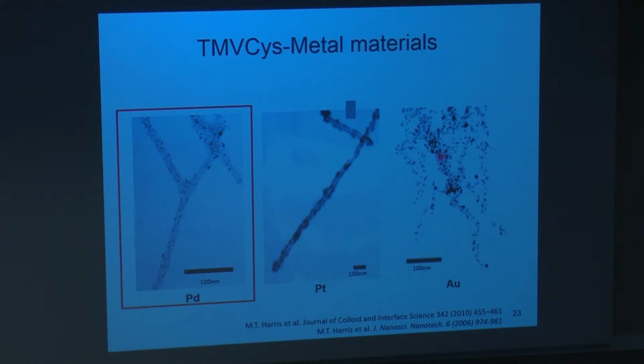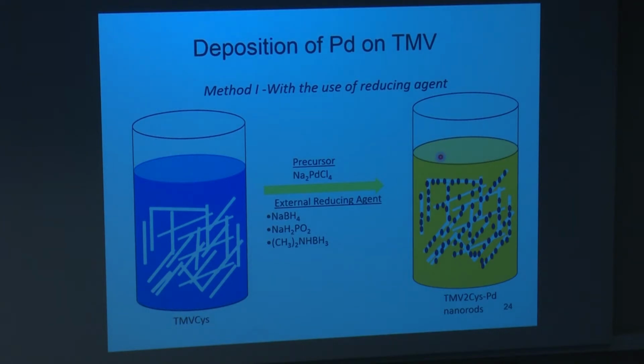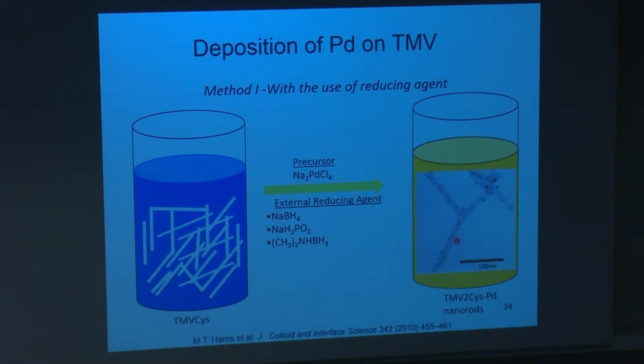So we decided to look at the palladium in greater detail. And as I said earlier, there are two methods. One, where you use a reducing agent, and some of the reducing agents are like sodium borohydride, sodium hypophosphite, and dimethylamine borane. So we can use any of these to reduce the metals. And as I said, the coatings weren't always uniform and so forth when we did that. So you end up with coatings that look somewhat like this on some of the viruses, but not necessarily all of the viruses.